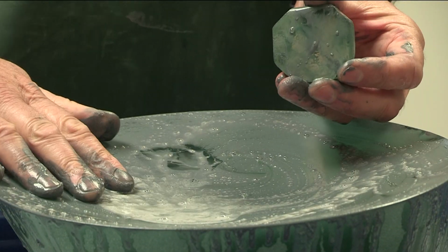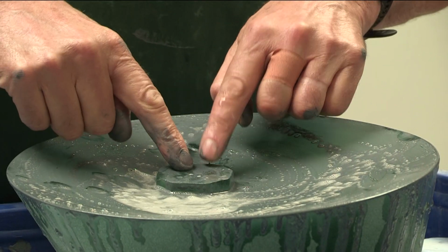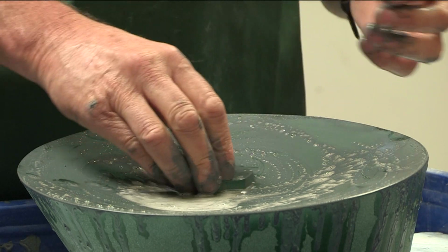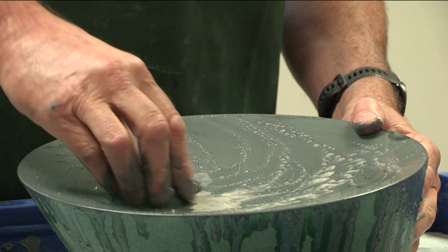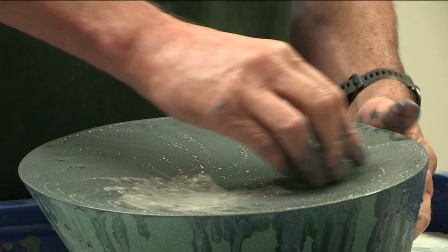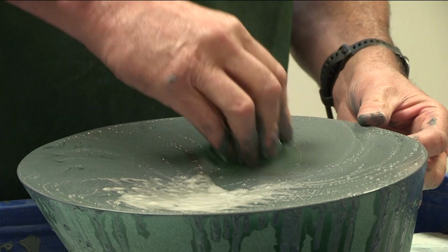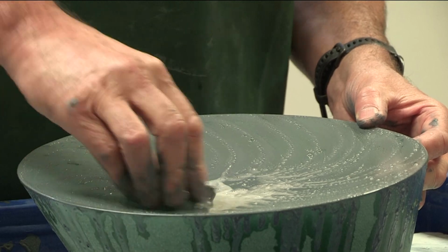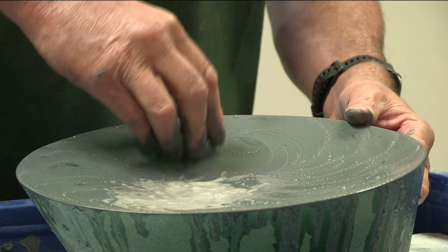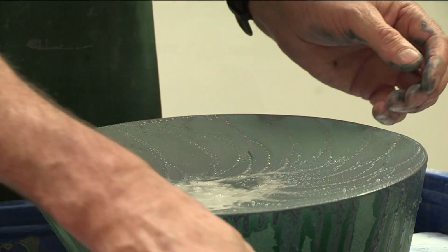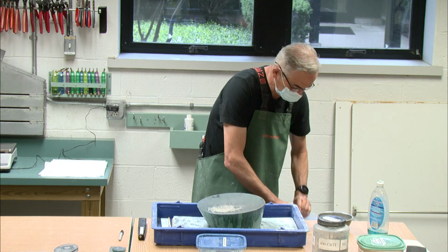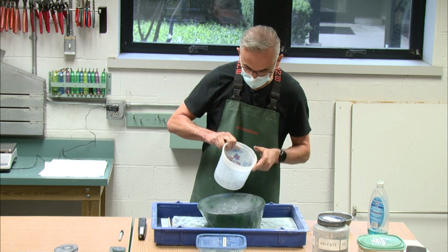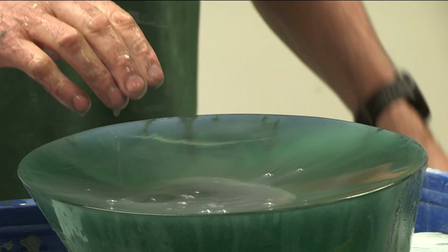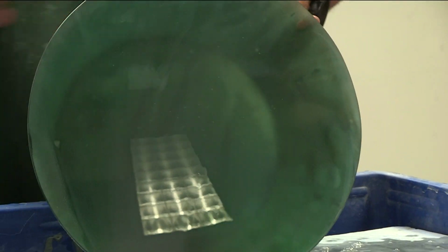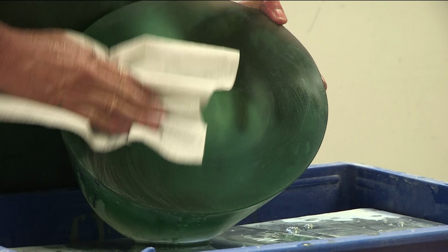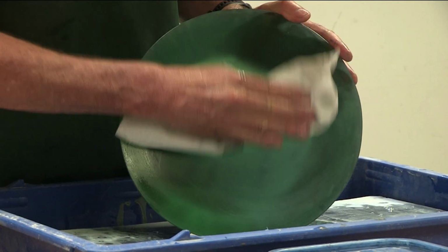And because I'm grinding 400 grit glass to glass, there's a hard surface here pushing against a hard surface there. So the grit is silicon carbide, it gets trapped in the middle and it abrades both this surface and this surface. So what we'll do now is we'll stop and we'll take a look at this surface. I'll just give it a bit of a rinse. I'll just dry that off.